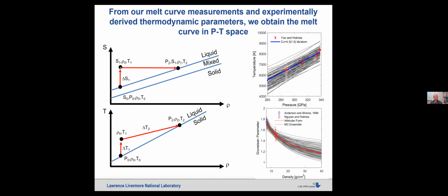So I am including the fact that the pressures will change, and I'm tracking that based upon second derivatives, the heat capacity and gamma. The isochoric heat capacity is easy to get from the slope of the Hugoniot. I wouldn't use an isobaric heat capacity because it is not as easy to derive from the Hugoniot. Does that make sense? Thank you.